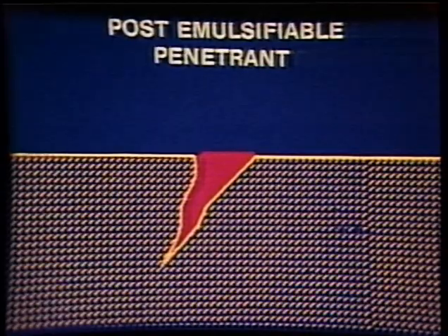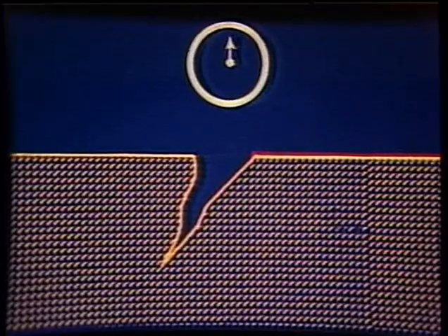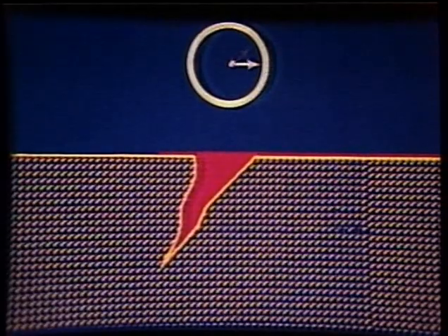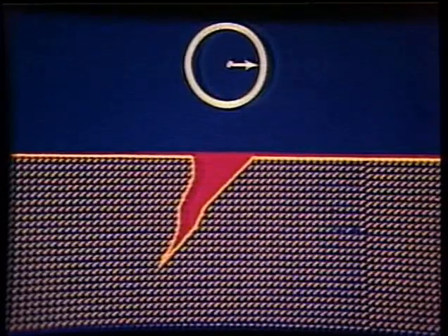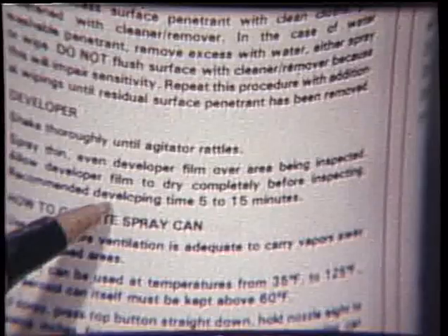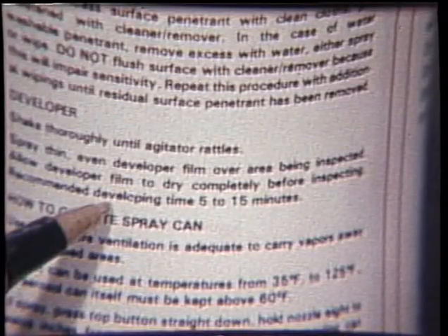for shallow surface discontinuities. Whatever form of penetrant is used, sufficient dwell time must be allowed, so that the penetrant can find and seep into any openings. The dwell time is based on the type of material and the degree of accuracy required. Longer times allow the flow of penetrant into more and smaller openings. Refer to the testing procedure or manufacturer's recommendations for specific times. Generally, the dwell time can range from 5 minutes up to several hours.